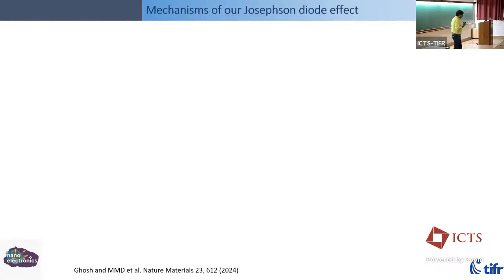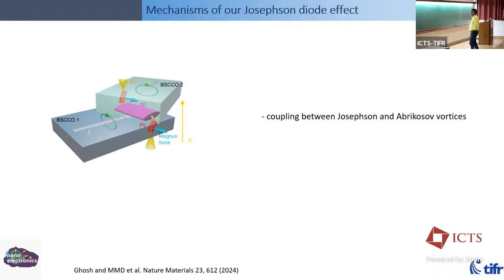So we spent quite a bit of time trying to think about the mechanism, and this work relies on two perspectives which are complementary. In high Tc superconductors, there are two kinds of vortices. One is Josephson vortices, which live between the planes of copper oxide, and vortices which are perpendicular to the copper oxide planes, which are called the pancake vortices. And when you twist, you are actually reducing the Josephson energy, because as you twist the two layers, the critical current or the switching current reduces because of the D-wave order parameter. Now, the Josephson energy gets reduced as a result.